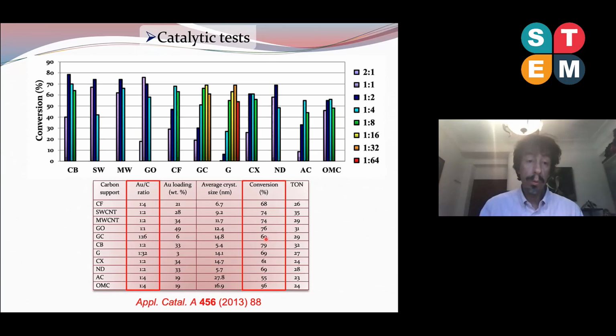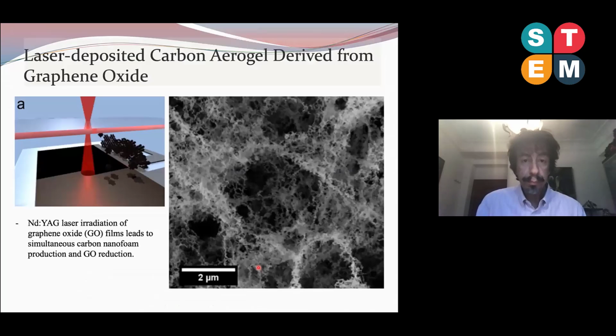And this is the case of our carbon foams, which provided conversion values comparable to the conversion values of other materials like graphitic cones or carbon gels or nanodiamonds. So we got nice results with our gold nanoparticle decorated carbon foams.